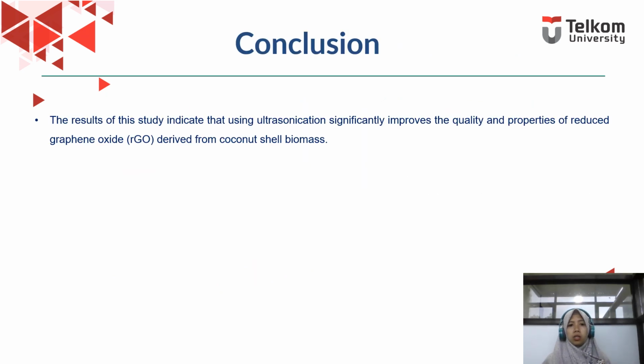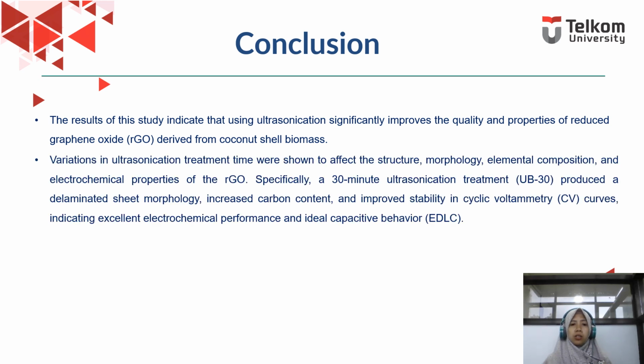Okay, this is the conclusion. The result of this study indicate that using ultrasonication significantly improves the quality and properties of reduced graphene oxide derived from coconut shell biomass, and then the variation of ultrasonication treatment time were shown to affect the structure, morphology, elemental composition, and electrochemical properties of RGO, especially 30-minute ultrasonication treatment produce a delaminated sheet morphology, increased carbon content, and improved stability in cyclic voltammetry curve, indicating excellent electrochemical performance and ideal capacitive behavior.